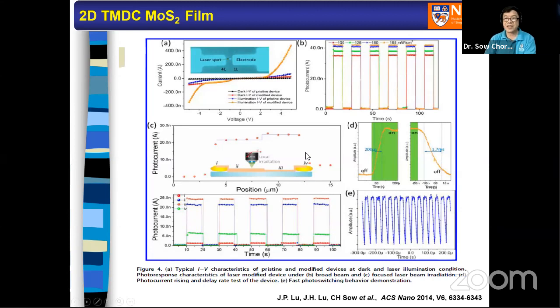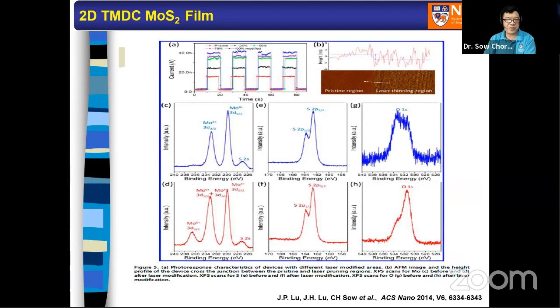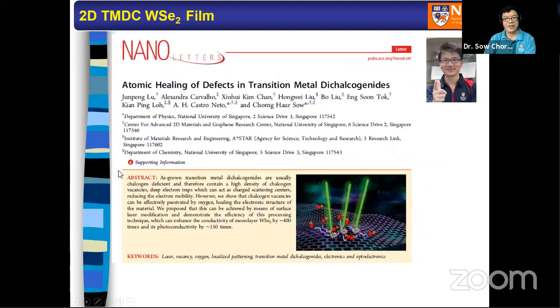We don't get MoS2 purely. We get MoS2 plus oxygen. Okay, this one is important. And we prove the presence of the oxidation state with XPS. You see, this is mainly pure MoS2, mostly Mo 4+, but with laser modifications, you have Mo 4+ plus a mixture of 6+ because MoO3, Mo takes the form of the 6+ oxidation state. And we can go from one to another.